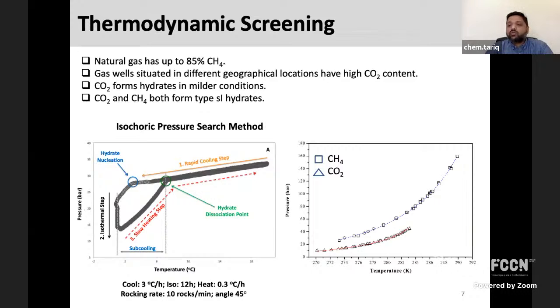We have used CO2 to form the hydrates. Most often, the natural gas contains up to 85% of methane, and that's why people generally perform these tests on methane. But there are different gas wells available even in Europe and in Southeast Asia, where the CO2 content in the natural gas is very high. And CO2 and methane both form type sI structure. That's why we have used CO2 gas for testing these ionic liquids.